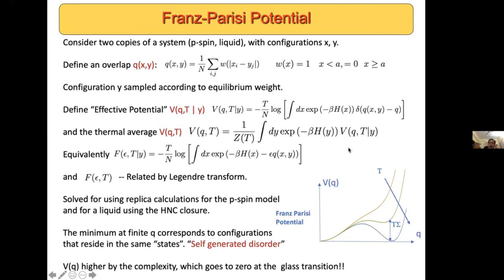And as temperature is varied from high to low, the behavior of this function is as shown, where in addition to the minimum at Q equal to 0, a second minimum at finite Q develops, and this corresponds to these two copies of the system sticking close to each other.